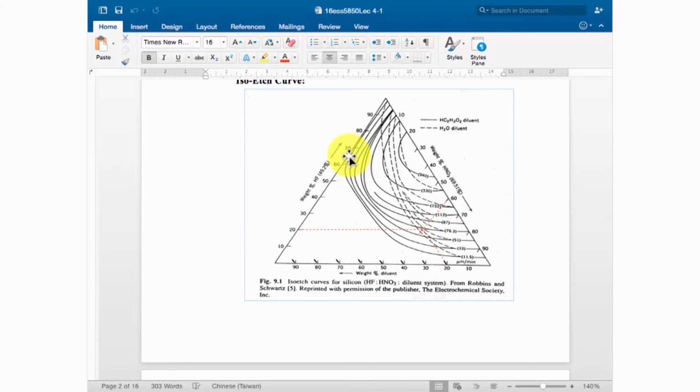But in the opposite, on the bottom portion, you have more nitric acid than hydrofluoric acid. The surface becomes smoother. Even though they share the same etching speed, the bottom one is smoother because you have a thick silicon dioxide layer all the time for protection, so you won't etch too fast.